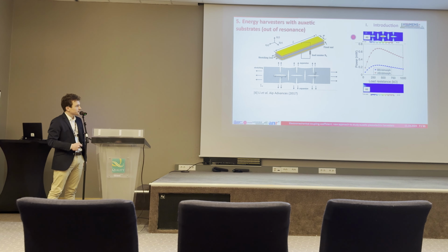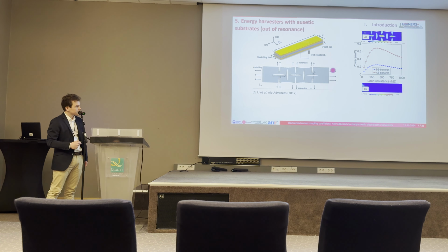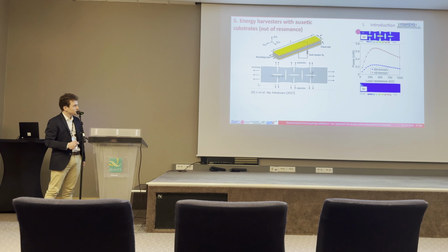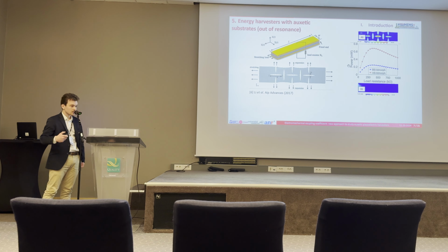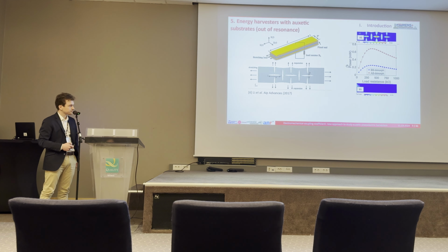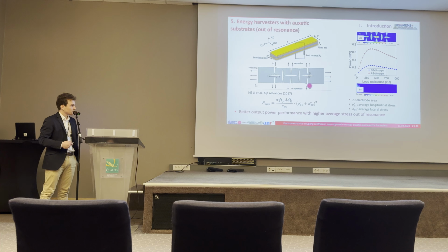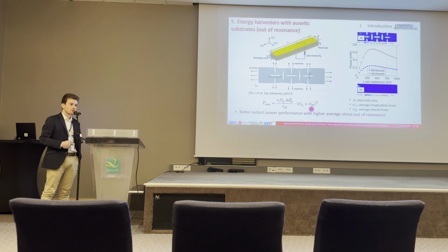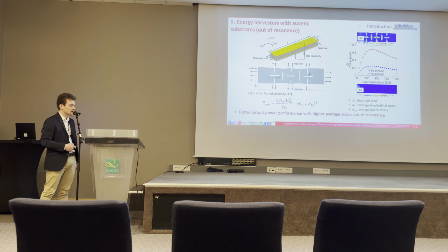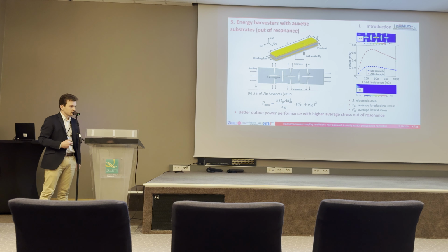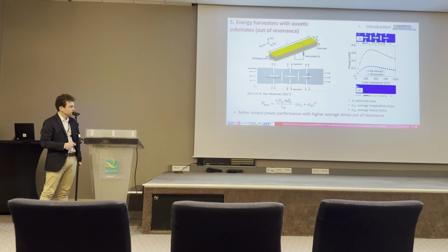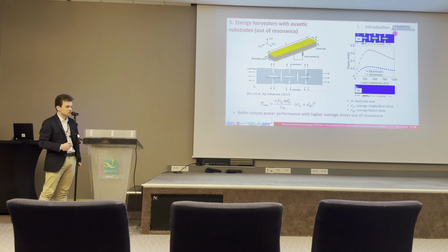You can see that they explain the power increase in the piezoelectric element thanks to some stress added to the piezoelectric layers. And so they give this equation saying that the maximum power is proportional to the squared stress. So it looks quite relevant: by adding stress we add power.